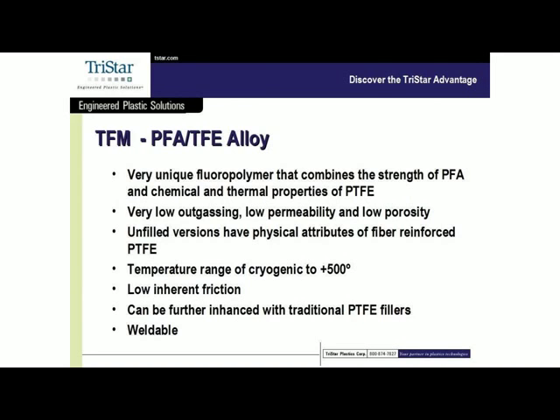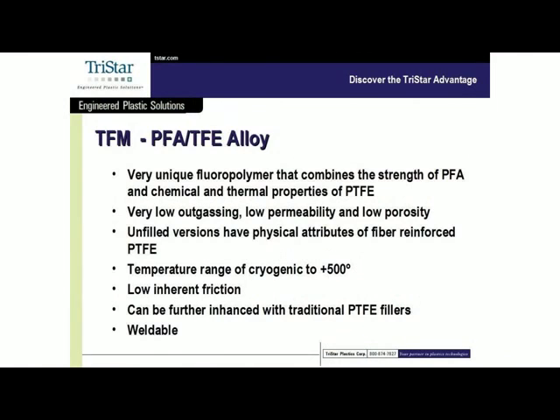Low permeability. Because it's a non-porous material, or very close to non-porous, it has very low permeability in gas and steam and in those environments. The low porosity also makes it a very, very good valve seat, for instance. And because of its low porosity and its additional physical strength from the PFA, TFM with no fillers actually has the same capabilities in terms of pressure and sealability of a carbon-filled Teflon or a glass-filled Teflon. So if you have a situation where you can't use fillers because of purity issues or something like that, TFM is a very good candidate for valve seats and stem bushings and things like that, where you've got a very pure material with excellent physical strength.